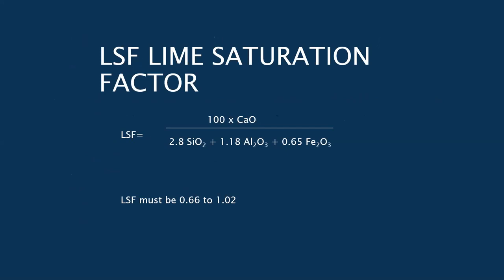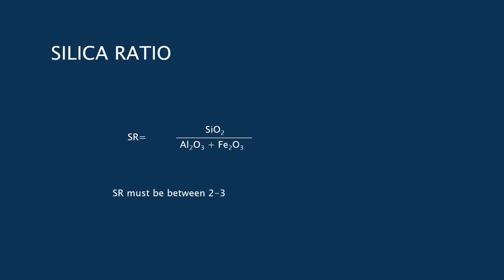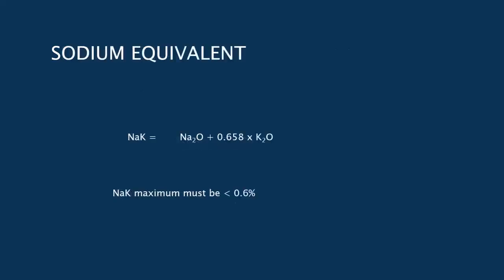Lime saturation factor is calculated by 100 times your CaO over 2.8 your silica, 1.18 your alumina, and 0.65 your iron. And we have got to control that in the cement industry to between 0.66 and 1.02 in your raw materials. Silica ratio, it's another thing that needs to be controlled, and that's calculated by your silica over your iron and alumina. That has got to be controlled between 2 and 3. Sodium equivalent, in the industry, is known as NaK. It's Na2O plus 0.658 times your K2O.